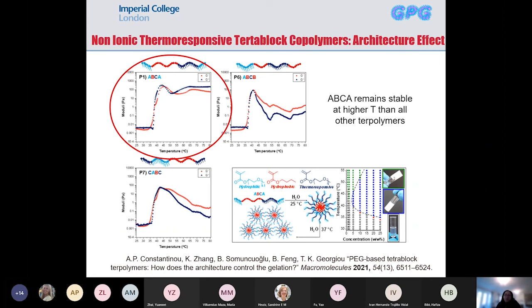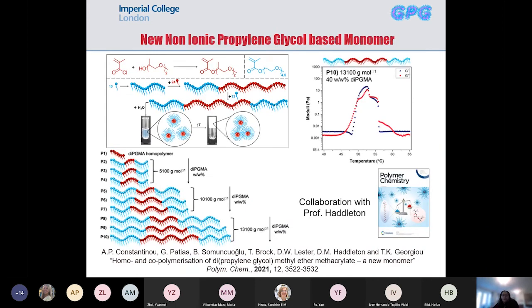Now, we've always tried to search for new polymers and monomers that we could use to make thermogels. In our latest study, we have actually synthesized a novel monomer. In our attempt to mimic pluronics, we synthesized a methacrylate polypropylene-based monomer, this one here, and we then made ABA polymers based on methacrylate PEG at the two ends and methacrylate polypropylene in the middle, similar to the pluronic structure, but this is a methacrylate equivalent. We've made polymers of different molar masses and different compositions, and one of them did form thermogels. Of course, it will take some time to tune this in order to form gels at the concentrations and temperatures that we want.